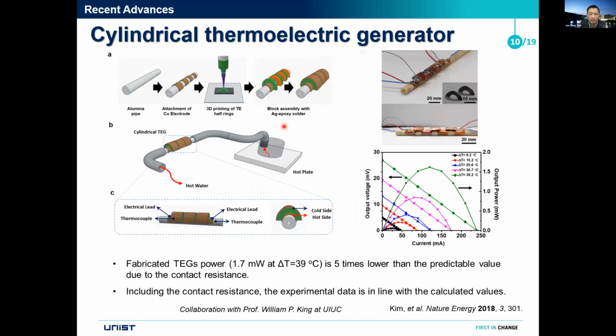So by using these inks, we 3D printed this curved structured thermoelectric material, which has dimensions perfectly fitting to this ceramic pipe. After mounting these 3D printed thermoelectric N-type and P-type materials on the ceramic pipe, we could fabricate a cylindrical thermoelectric generator. We measured the power performance by flowing hot water through this pipe, and you can see a reliable output power depending on the temperature difference. In this paper, I have collaborated with Professor William King.